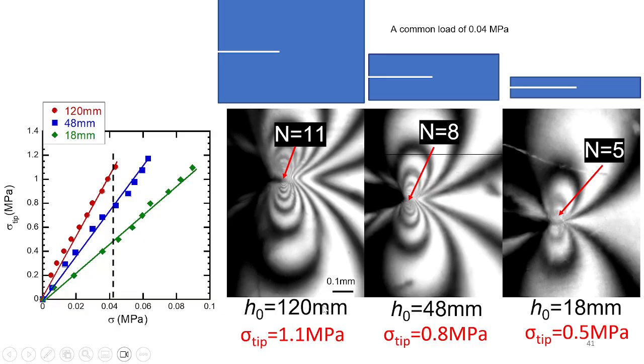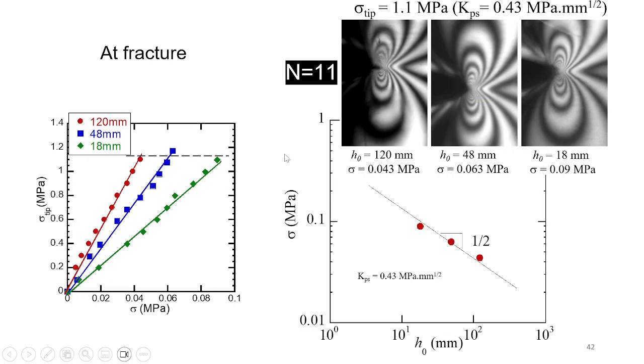Okay? Similarly, when the crack propagation occurs, you find that it's independent of the H you used. In other words, the higher H involves a smaller load. Okay? At the crack propagation, the tip stress condition is the same. So this indicates it is all about how the stress is dictating the breakup of the network at the tip, rather than an energy argument.